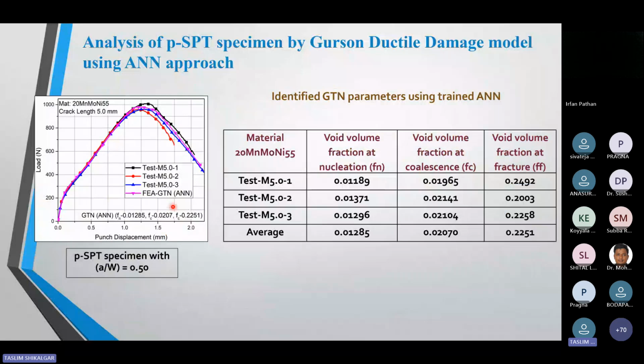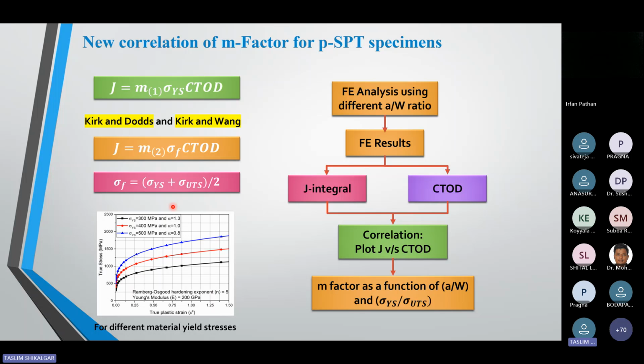Now the important task. I told about the J integral as well as CTOD. CTOD is the crack tip opening displacement. The second one, the American approach, is the J integral. J integral is the energy release rate calculated in ductile material. J integral is divided into two parts: one is the elastic part and the second one is the plastic part. The elastic part is known as the stress intensity factor, which is an important parameter used in brittle materials. And J integral is the non-linear energy release rate, which depends on the path.